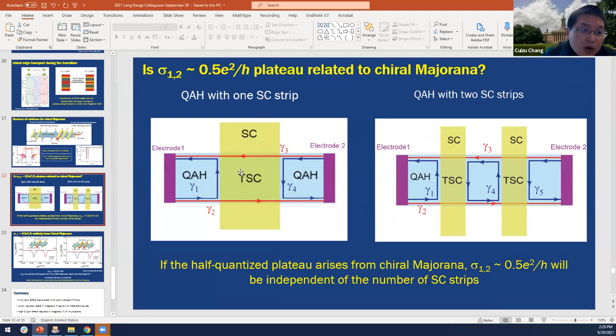And as David just said, if we want to induce chiral topological superconductivity here, we need two things. One is we need the proximity effect between the chiral edge state and the superconductor layers. And we also want to avoid the shorting effect between the two chiral edge states. But as an experimentalist, in the millimeter size, the superconductor always shares the same chemical potential if there is proximity effect. In very highly transparent quantum anomalous Hall and superconductor layers, I don't think this kind of hybrid structure is good, because it should always short in millimeter size.